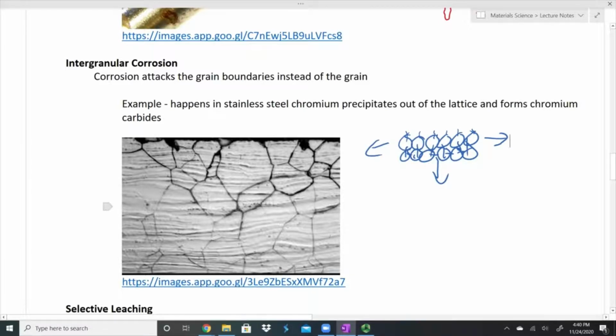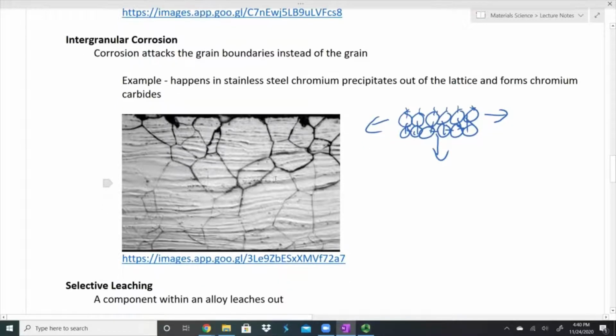We no longer know necessarily what percentage of stuff we have in here, but what's worse is it precipitates to the grain boundaries. And so in these grain boundaries, we actually get these chromium carbides that just sit there, and those don't bond as well as these grains bond to each other. It weakens these grain boundaries and can cause failure.